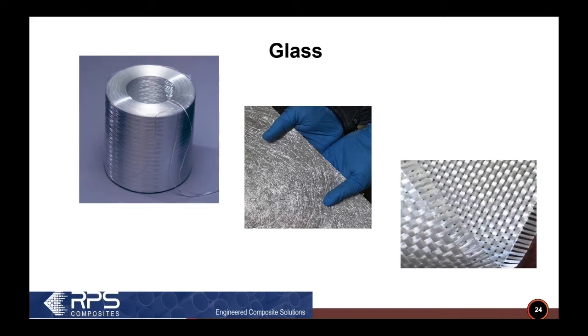So what the glass manufacturers do is chop up that roving, spray it down, and spray a binder to hold it in place. And what you get is something called chopped strand mat. That's what's shown in the middle of the picture. That chopped strand mat is great for corrosion resistance because the glass fiber is chopped up, and that makes it much more difficult for chemicals to get through the glass reinforcement to wick along the fiber.